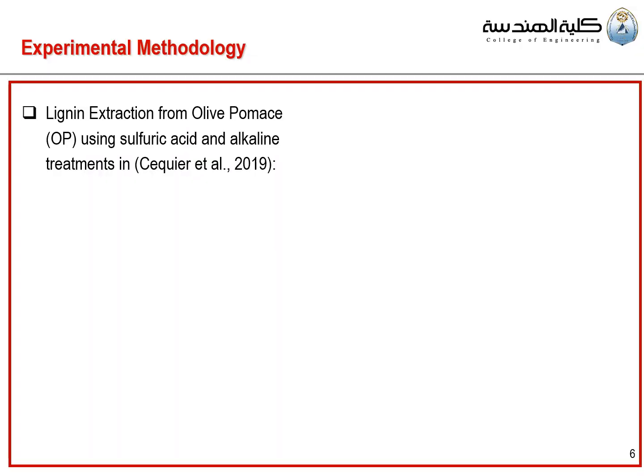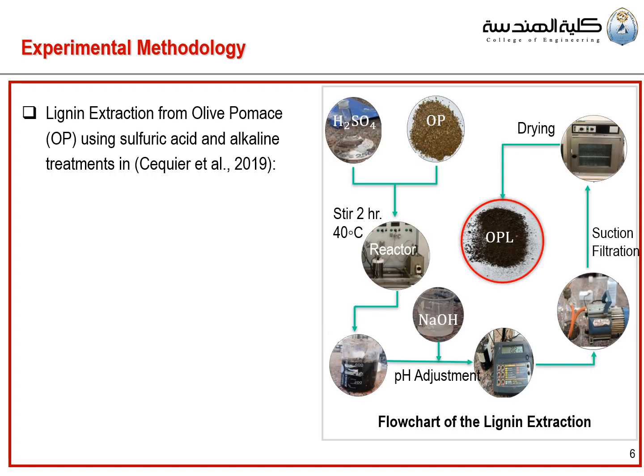For this slide, I will not waste a lot of time. This is about lignin extraction, if you are interested. It went through sulfuric acid and alkali treatment using an existing chemical method. We basically mix the olive pomace with the sulfuric acid in the reactor and do some alkali treatment and pH adjustment using NaOH.